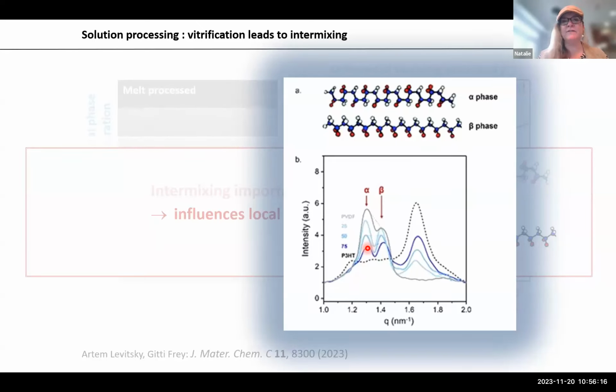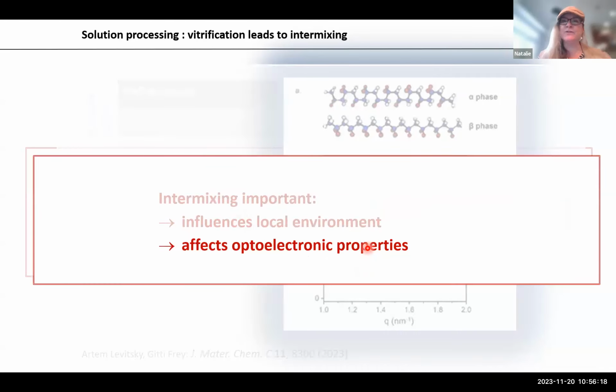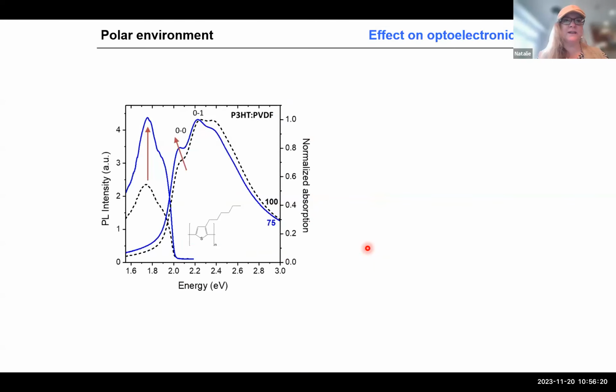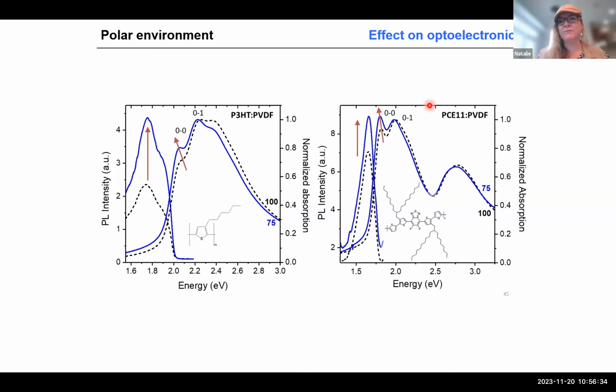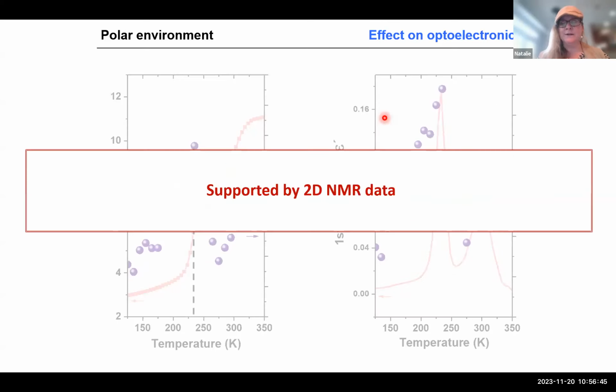So blending definitely has an effect on the materials, and we see that also optically. So, simple photoluminescence and absorption spectra. In absorption, you see the 0-1 transition goes up. In PL, it massively increases once you blend. It's pretty universal, whatever polymer we use. So this is another thiophene derivative. PL goes up, the 0-0 goes up.